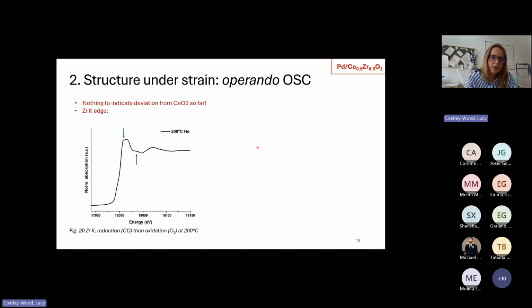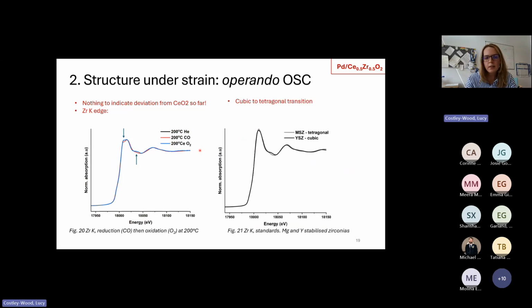So this is the spectra at 200 degrees in helium, and this is at 200 degrees in CO. And these changes seem very small, but they are significant. They're also reversible, so when we put the oxygen on again, we go back to our initial state. Looking at the literature and comparing to standards, we see that this transition here is really indicative of a cubic to tetragonal transition. So we have local disorder around the zirconium in terms of zirconium-oxygen bond lengths changing and becoming less equal, and a symmetry loss, very localized, but on the macro scale, for example, by powder diffraction, the symmetry of the material is retained. And this is what's been predicted by DFT over 20 years ago, but hasn't been shown yet.